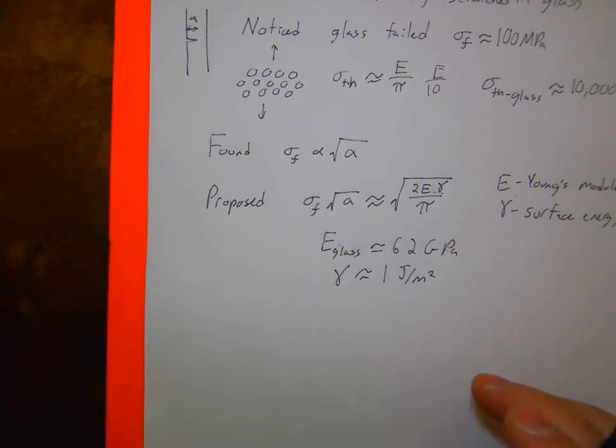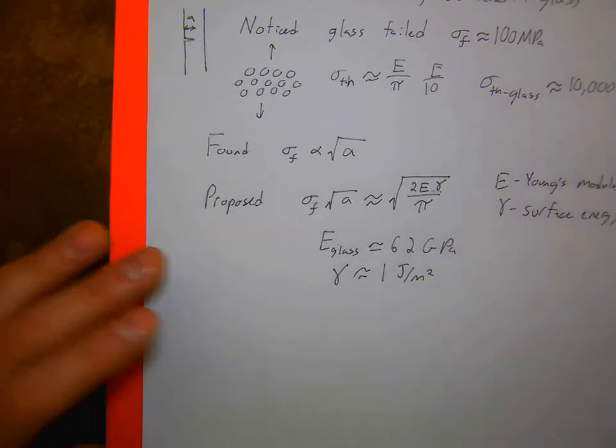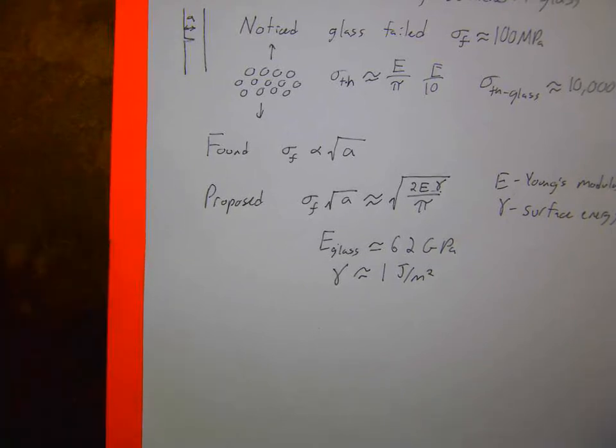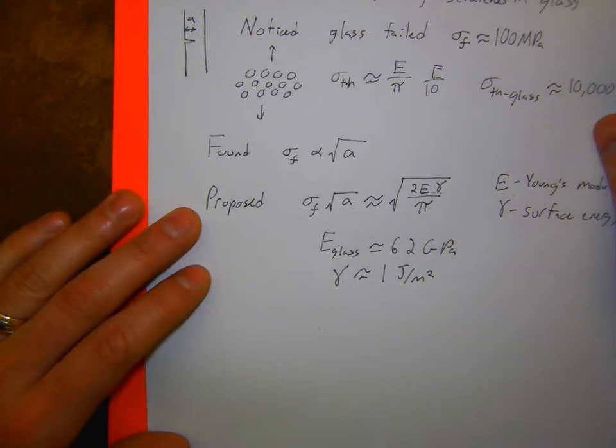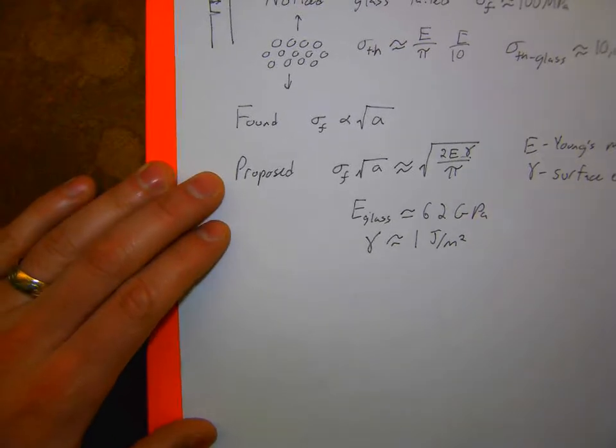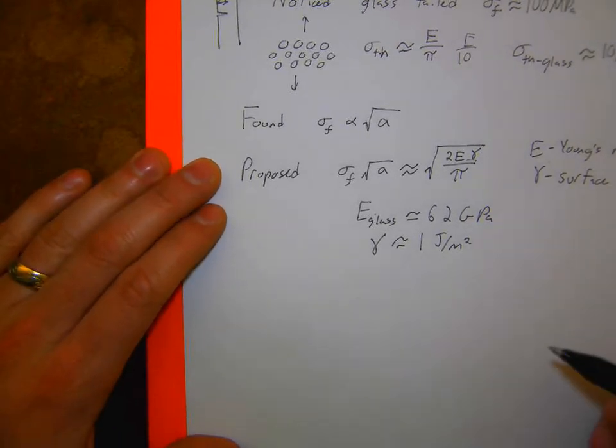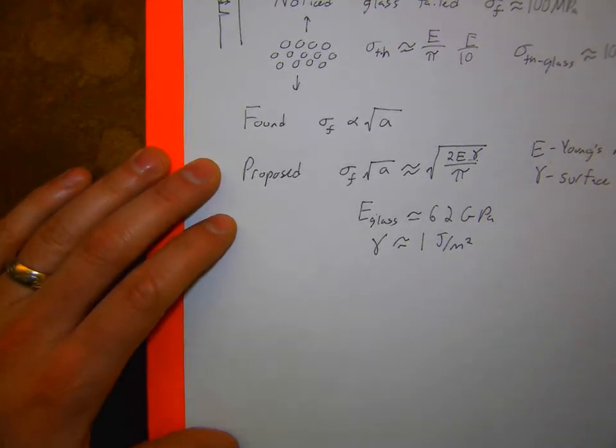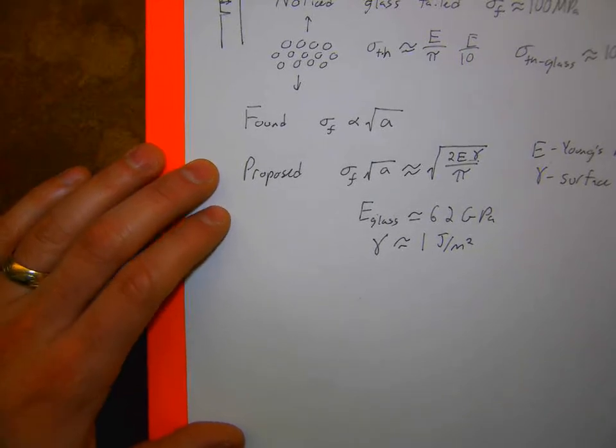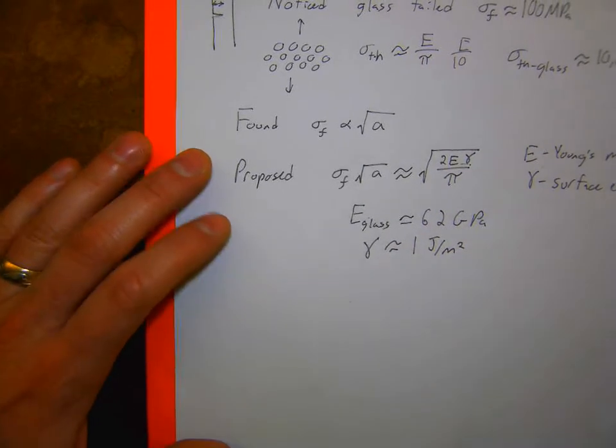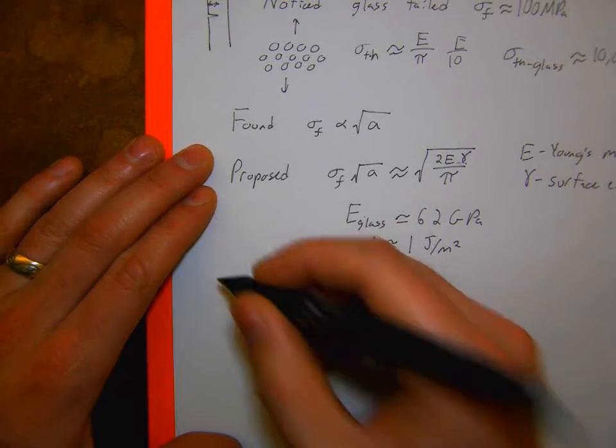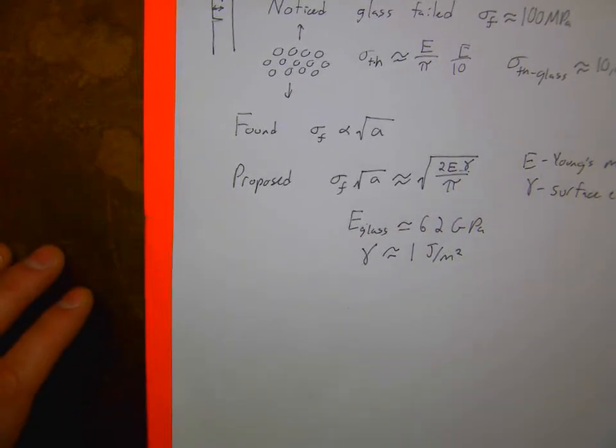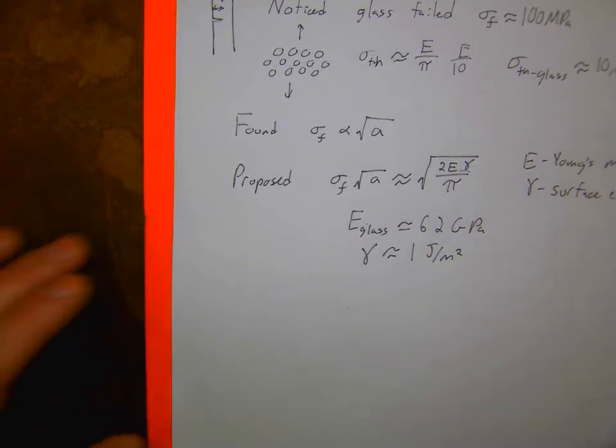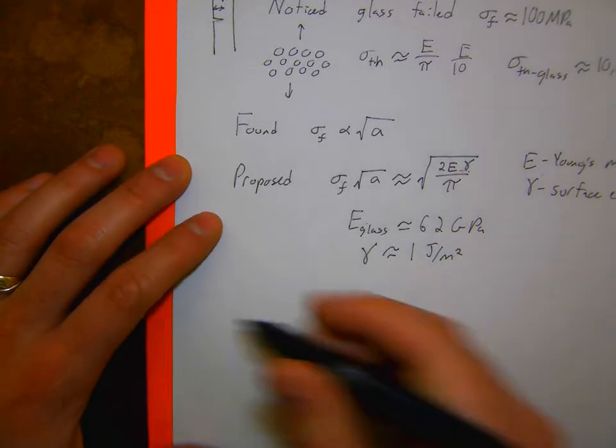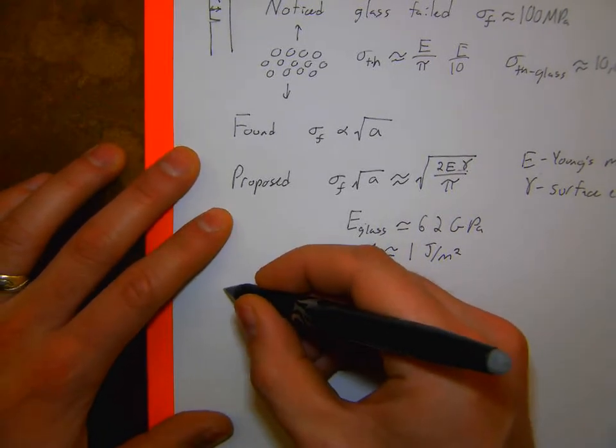So after that, this theory kind of sat around for a little while. So from Griffith theory, we're going to define now a fracture or a stress intensity factor. So for the stress concentration, I had showed a KT, which was the ratio between the maximum stress and the far field applied stress. Here we're going to use a similar idea, and we're going to define a stress intensity factor.